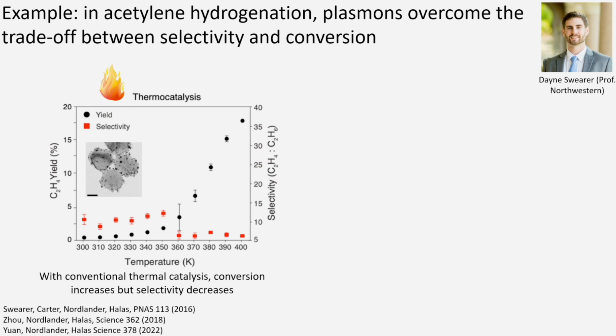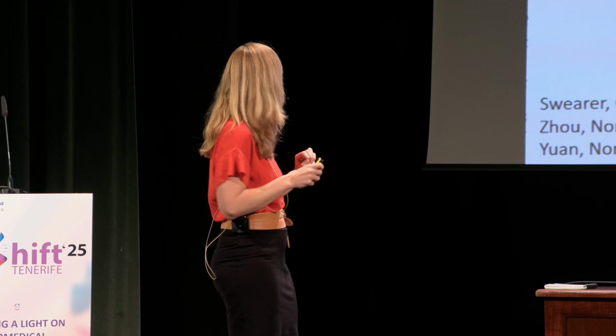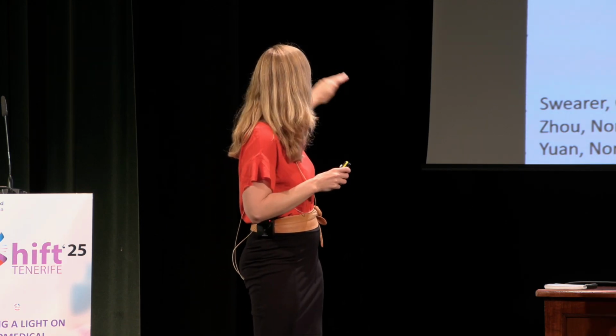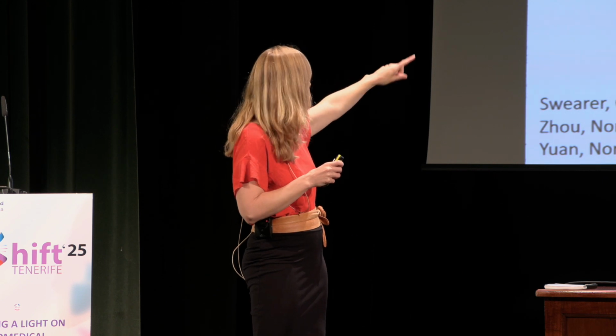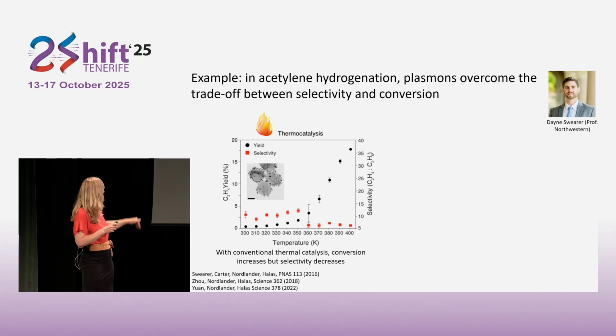So this is some work done by Dayne Swearer, who was a PhD student with Naomi Halas at Rice University. He then came to my lab as a postdoctoral fellow. But here he was looking at acetylene hydrogenation to create ethylene, basically a precursor to polyethylene. And if you look at traditional thermocatalytic processes, using again those silver and palladium nanoparticles that I just showed you, basically the yield of the ethylene you get goes up, showing the increase in temperature in black here, while the selectivity in red generally goes down.